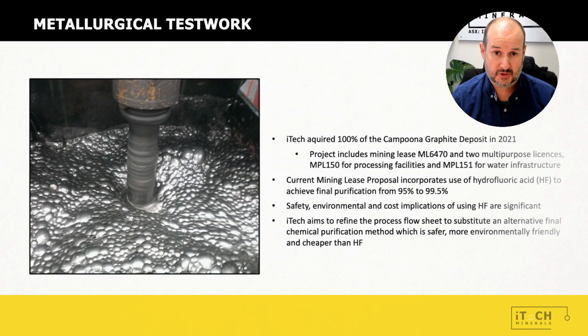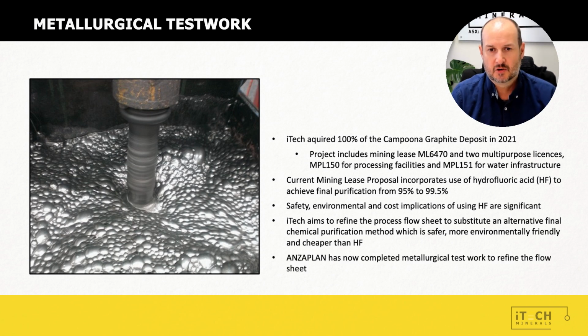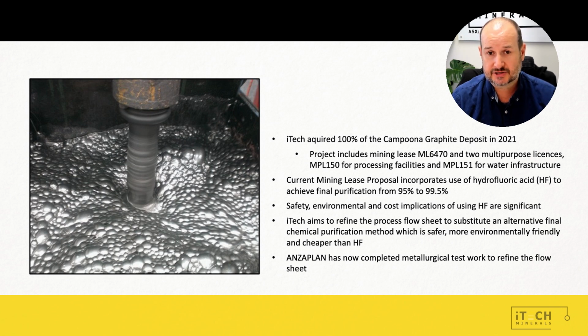But what we knew was that final purification stage, which used hydrofluoric acid, had the potential to have problems from both a safety and an environmental standpoint. So what we wanted to do was substitute that final purification stage from 95 to 99.5% from hydrofluoric acid into another process which has a lot better safety, environmental and cost implications. So what we settled on with Enzaplan was to trial a caustic leach or autoclave assisted caustic bake process. So very early this year, we were able to send approximately 600 kilograms of run-of-mine material from CAMPOONA over to Enzaplan in Germany to undertake this metallurgical test work.